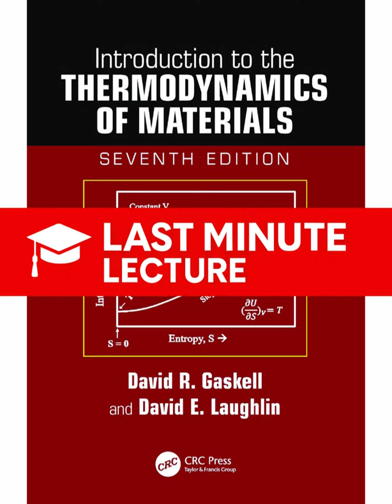Whoa! Okay, a second derivative. Let's unpack that because that is not intuitive at all. Why on earth does heat capacity relate to the second derivative of free energy? Well, think about it this way. What's the first derivative of Gibbs energy with respect to temperature? That's entropy, S. Negative S, actually.